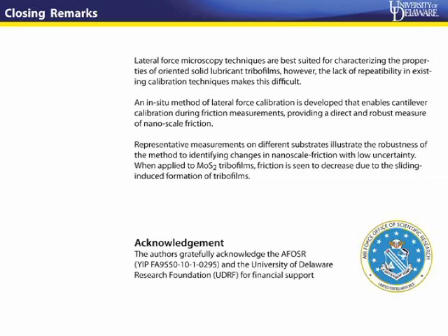So essentially what we've done is develop this method, and we believe that reducing all those uncertainties that I mentioned provides for a more robust quantitative friction measurement in what is otherwise a really challenging set of techniques in lateral force microscopy: getting accurate quantitative friction measurements.